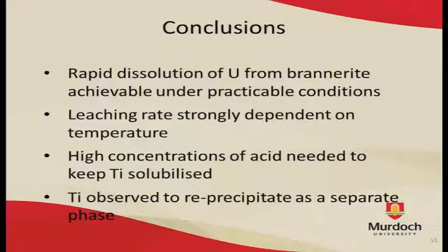So going back through the main points, rapid and complete uranium dissolution is achievable with this sort of mineral phase. The rate of dissolution is very much dependent upon temperature. Titanium will dissolve along with uranium, but it doesn't necessarily stay in solution for that long, forming a secondary titanium oxide phase. The concentration of acid has quite a strong effect on the amount of titanium that will dissolve and stay dissolved. And when it does precipitate out, it does so as a separate phase, not on the surface of the brannerite as we'd initially been concerned.